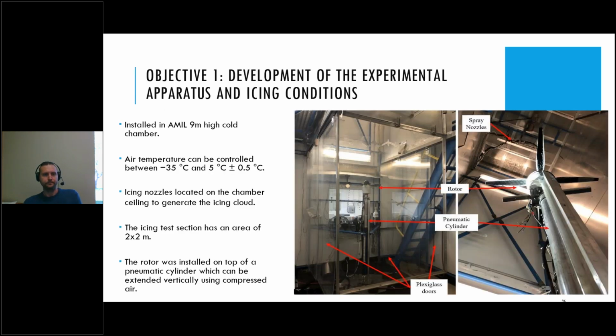Next slide, please. So we installed the rotor in a 9 meter high cold chamber where the air temperature can be controlled between -35 and 5 Celsius degrees. We have icing nozzles located on the chamber ceiling to generate an icing cloud. The icing test section has an area of 2 meters per 2 meters, surrounded by plexiglass doors. And the rotor was installed on top of a pneumatic cylinder, which can be extended vertically using compressed air to test at different heights. So different distance from the ground, different distance from the nozzles.